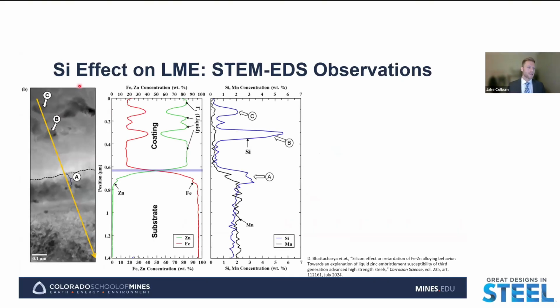And then if we zoom in a little bit and take a look at a TEM lift out of the interface of that high silicon containing cross-section of the hot tension sample. So here we have a STEM EDS line scan. So this is scanning transmission electron microscopy, energy dispersive spectroscopy scan through here, where we see the composition of this line as we move from the top of this region of the coating into the substrate.